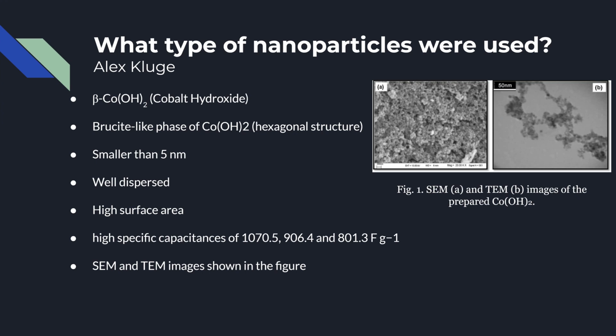The nanoparticles are also ultrafine particles with sizes smaller than 5 nanometers. The nanoparticles are well dispersed throughout the solution, and additionally, they were found to have porous morphology. These factors work together to create excellent energy storage ability for the nanoparticles.